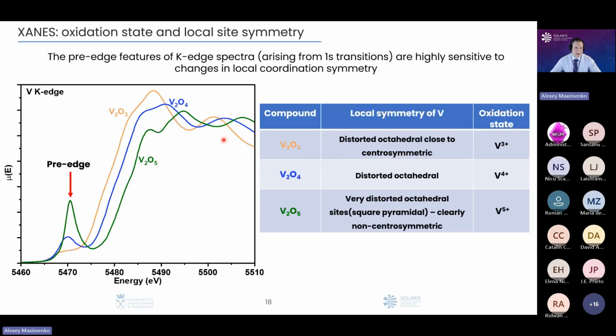Also, when we speak about the XANES region, we could easily investigate the local coordination symmetry in our materials. For example, here you could see a quite symmetric local symmetry. For vanadium 3 oxide, we could investigate it by looking at the intensity of the pre-edge peak. It means some feature before our main absorption edge. Here, for vanadium 3 oxide, the pre-edge is very low, which helps us understand that in this phase we have a quite low level of distortion. In comparison, for example, to vanadium 5 oxide, where we have a clearly non-centrosymmetric local structure, and in this case the intensity of the pre-edge is quite high.